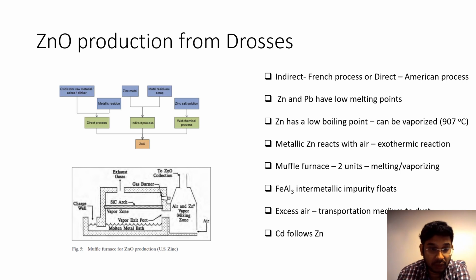So one of the typical examples is the usage of this muffle furnace, where you have essentially two chambers separated by a sort of arch. You have the charge going in, and then you have the charge heating up, with a molten metal bath, and then you have the vapor zone. And once you have produced a vapor, the zinc vapor travels into what could be called a combustion zone. Okay, so the zinc combines with the air and then forms zinc oxide. It's as simple as that. And then you collect the zinc oxide in one chamber or the other. So it literally boils down to this very simple chemistry.